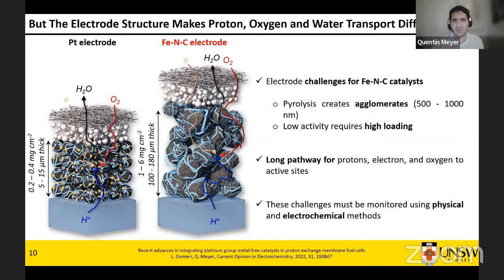So the first problem is that the way it's synthesized, it's typically done taking a metal organic framework on which you dope some iron, and then you carry out pyrolysis. And depending on how you pyrolyze it, material particles are going to stick together and create some large agglomerates. That's why the particles over there in this schematic are much larger than they are here. And not only do you have large particles, but you need a much higher loading, so a lot more volume. And that gives you a lot of problems.